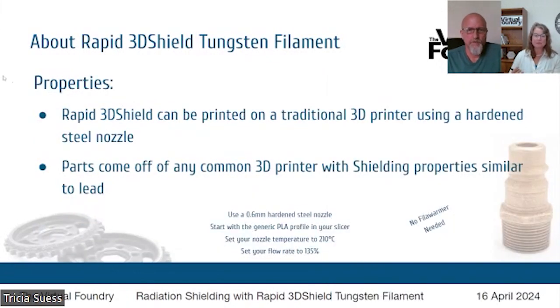Now, getting into some of the properties of Rapid 3D Shield Tungsten Filament. Because the Virtual Foundry's metal filaments use a PLA-based binder, they print just like PLA. If you're already printing PLA, the switch to metal filaments is a breeze. And Rapid 3D Shield Tungsten Filament is no exception. In fact, it's one of our easiest materials to print, surprisingly, along with being the most dense 3D printing filament that we make. You'll use a 0.6 millimeter hardened steel nozzle, select the generic PLA profile in your slicer, change your nozzle temp to 210, and the flow rate to 135%.